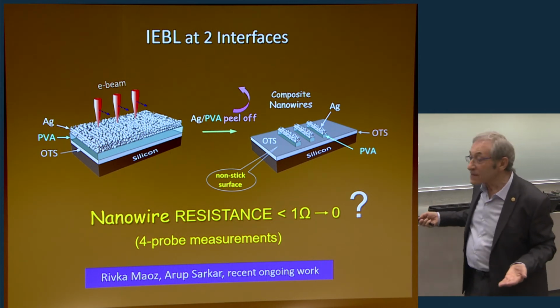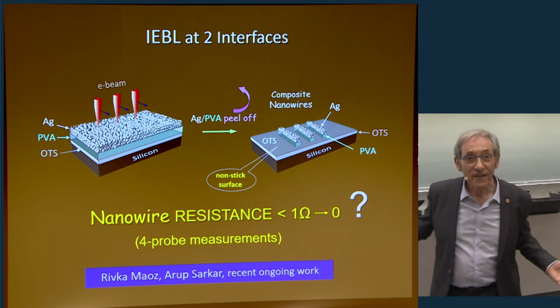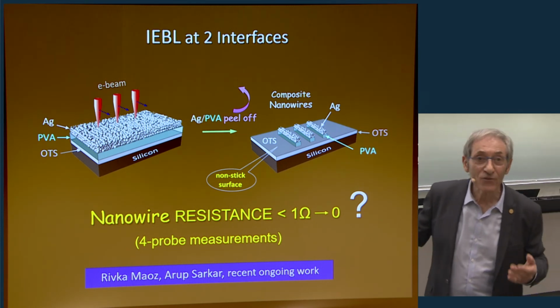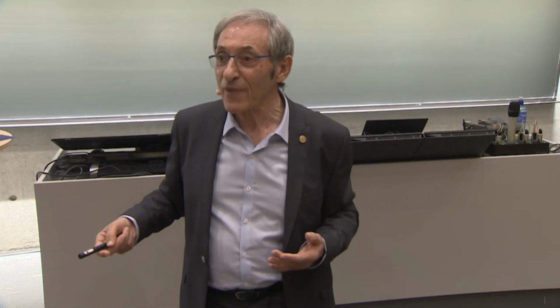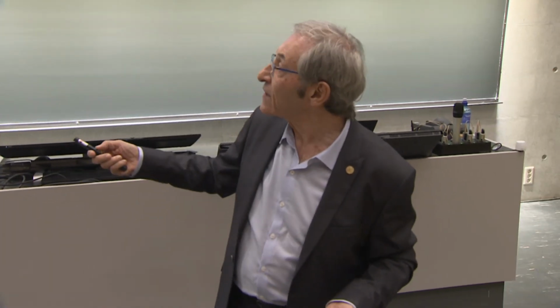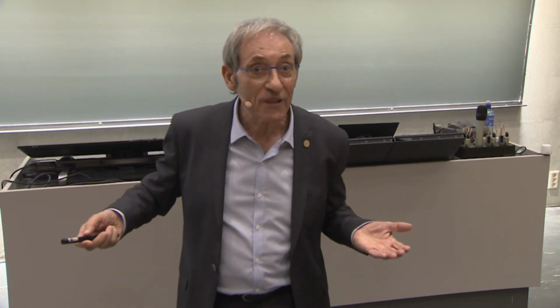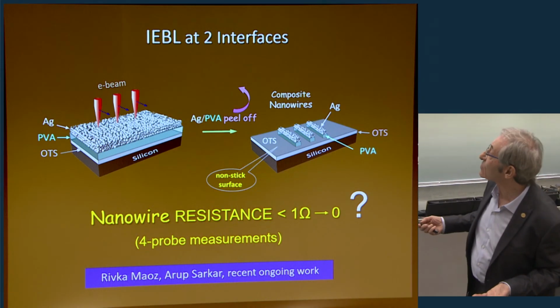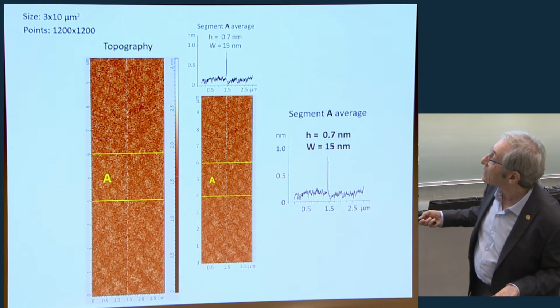So what is this? This is extraordinary conduction. Even if we make a calculation, it is 5 orders of magnitude at least higher than bulk silver, if we take into account the size. We have to decide what the size is using AFM, but AFM doesn't tell us the entire story. And what the AFM shows is the following.